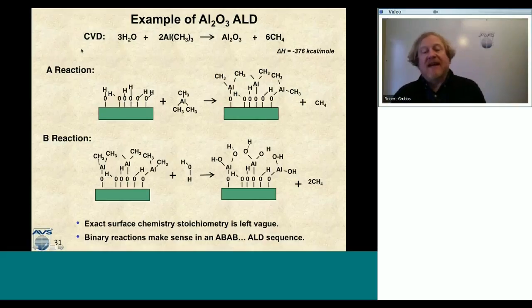Now notice that I've left the exact surface chemistry stoichiometry vague, whereas in CVD I can write actual reactants and products, and I can do the mass balance of either side of the equation. In ALD, the chemistry is left relatively vague. So if you see it in the literature, I wouldn't belabor that point, but just get that the chemistry is there. And also, the binary reaction sequence makes sense in this AB-AB format to put down materials that have two components in them. So if I have aluminum oxide or titanium nitride, I'm putting down two elements in my film and I'm running it in two AB-AB reactions. So that really makes sense in this AB-AB sequence.